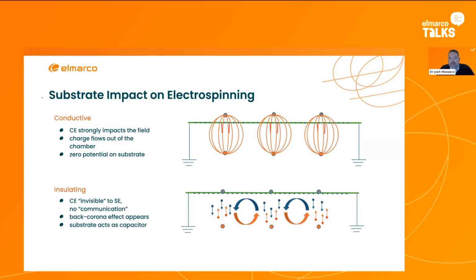But in the case where you have a material that, like I was mentioning before, is highly resistive, it's completely blocking the two, and you're forming a barrier between the two electrodes. And you're not going to get good spinning, or you might get some very light coating, but it's not going to be uniform, and it's going to be quite a mess, most likely, in your equipment.